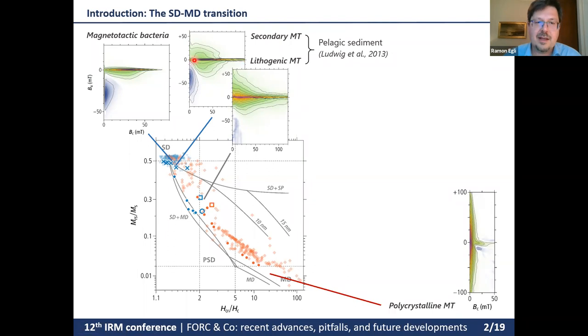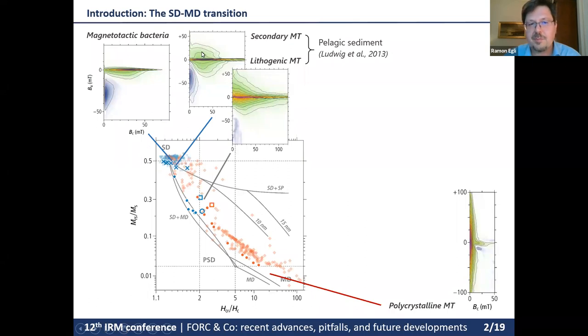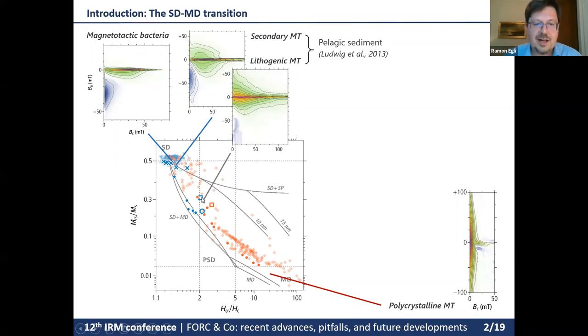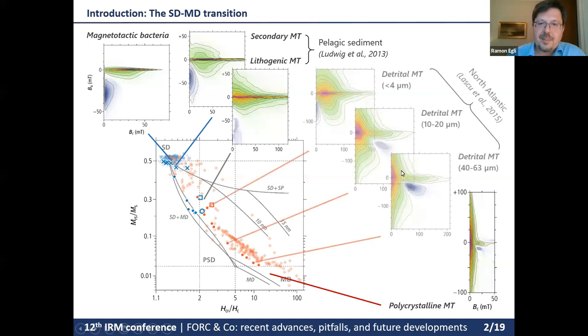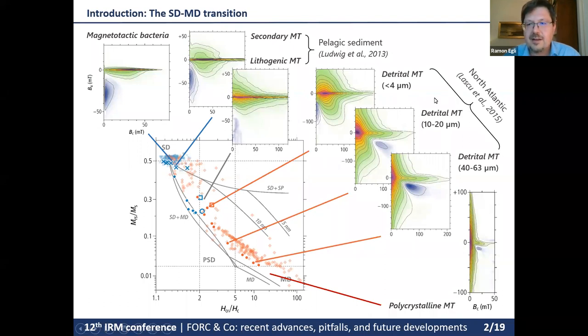This is the typical signature of magnetofossils: we have a central ridge, but also two contributions above and below the central ridge that have never been completely clarified — we will discuss them later. We also have lithogenic particles, which are very fine, mostly single domain, and visible in the central single domain range of the FORC diagram. Then we have a series of sorted magnetites from the North Atlantic, showing magnetites of increasing sizes.